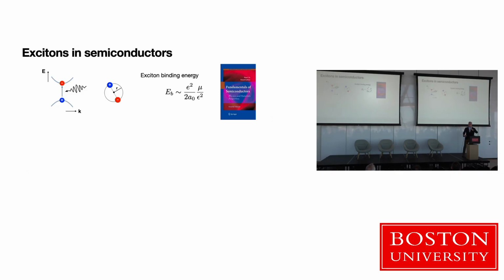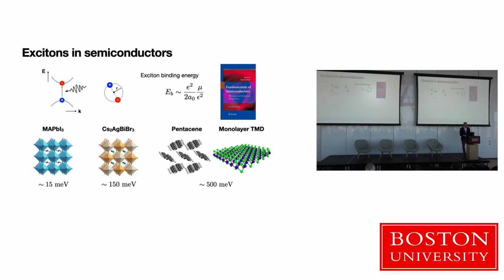Often to make the material functional, you want to separate the electron and hole. So it's kind of relevant. This binding energy is a relevant quantity for these materials. And just to give you a sense, these are a certain set of materials. These are two types of perovskites on the left, and an organic crystal and a 2D material on the right. And you can see the binding energies in millielectron volts listed here.